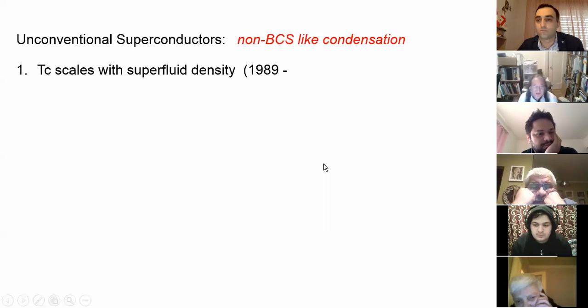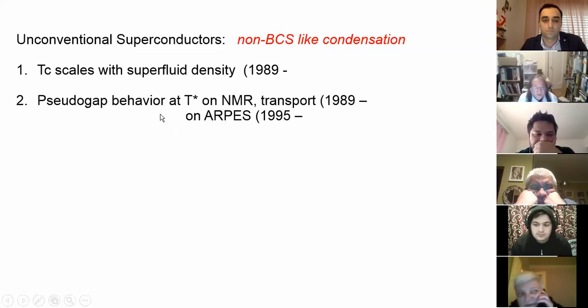The first one is that the superconducting transition temperature, TC, scales with the superfluid density. This I will show you soon. And this is what we discovered in 1989. And this is not what is expected in simple metal BCS superconductors. The second difference is showing up in something called pseudogap behavior. And this is measured by nuclear magnetic resonance or angle resolved photoemission. This also came out about two years after the discovery of high temperature cuprate systems.